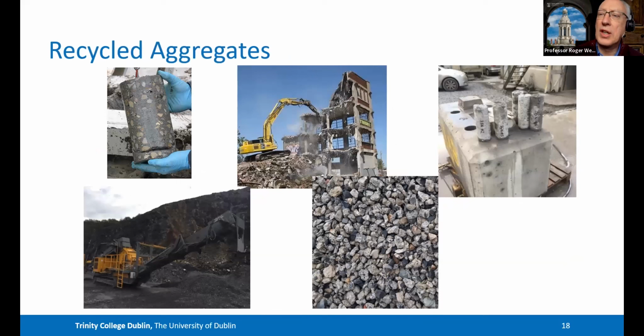I should say a word as well about recycled aggregates. The tradition has been that when you demolish a building, you've got demolition waste, and you might crush that down and recycle it and use it for low-grade materials. Whereas what we've been doing is getting into buildings before they're demolished, working with the demolition contractors and taking cores and establishing which are the strongest parts. So you might have a 30, 50 and 70 megapascal concrete, and then segregate those at source as you demolish and then send them for crushing so that you have a pile of high strength aggregate, which might be used in structural concrete, and then low-grade strength recycled aggregate for other applications.